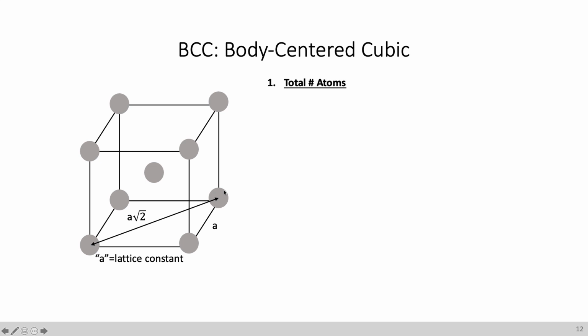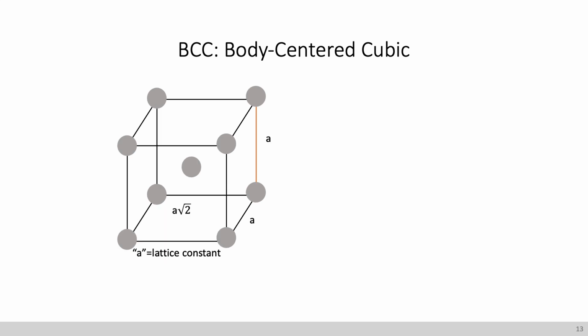And we find the total number of atoms for body-centered cubic, BCC. We find that again, at the corners of the cube, 1/8 times 8, because 1/8 of the volume of the corner sphere is enclosed within our cube structure. And because we have an atom already within the BCC cube, we have one whole sphere times one whole atom in the BCC structure. And so therefore we have 1 plus 1, which is equal to 2 atoms enclosed within our body-centered cubic BCC structure.